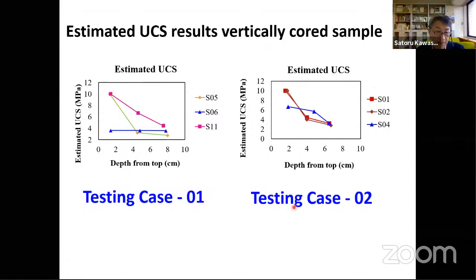This slide indicates testing case 1 and testing case 2, the estimated UCS, and depth from the top. This is the data obtained by needle penetration test. As you can see, the estimated UCS decreases with depth from the top.